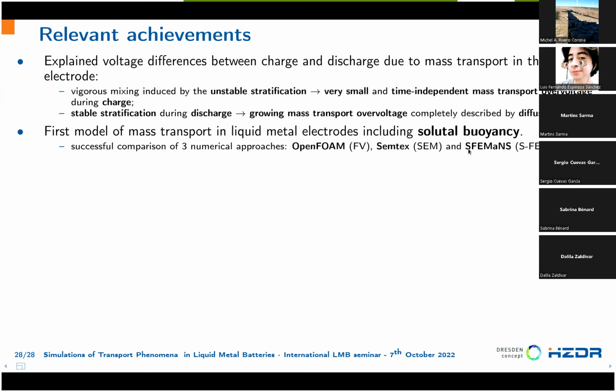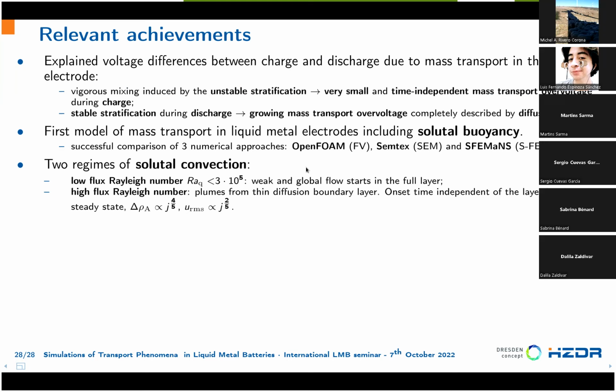So we include for the first time solutal buoyancy inside our mass transport model, and we use 3 different approaches: OpenFOAM, Semtex, and SFEMaNS. We discover 2 regimes of solutal convection, one at low flux Rayleigh number that is characterized by a global flow that starts in the full layer, and one at high flux Rayleigh number that is characterized by a thin diffusion boundary layer, and where plumes are present. And we have the scaling with this 4/5 and 2/5 power for concentration differences and velocity respectively.